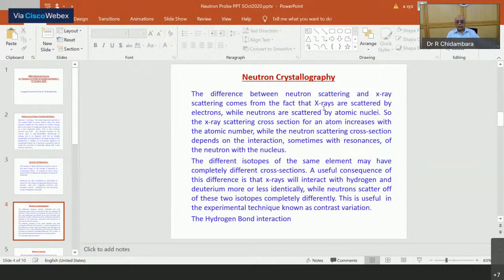If we look at neutron scattering and X-ray scattering, the main difference comes from the fact that X-rays are scattered by electrons, while neutrons are scattered by atomic nuclei. So in any material, the contribution of atoms with lower atomic number is much smaller than the contribution from atoms with higher atomic number. Whereas in the case of neutron scattering, the neutron scattering cross section depends on the interaction of the neutron with the nucleus, and sometimes there are resonances. In fact, it does happen that the different isotopes of the same element may have completely different cross sections.